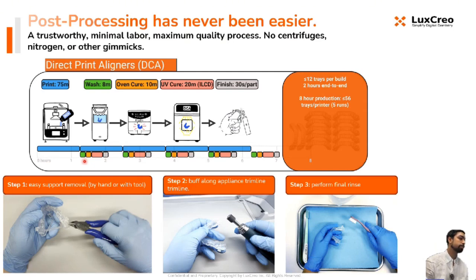But we recommend a heat treatment, or require a heat treatment for direct print aligners, because our glass transition temperature is really high. It's one of the main reasons why the aligners can move teeth really well. But when your glass transition temperature is high, it means that the parts need to heat up in order to fully cure. And then from there we have our UV cure step, and it just undergoes a traditional UV cure treatment. It takes 20 minutes, and then once that's done, you finish the parts, and it takes about 20 to 30 seconds to finish the parts,